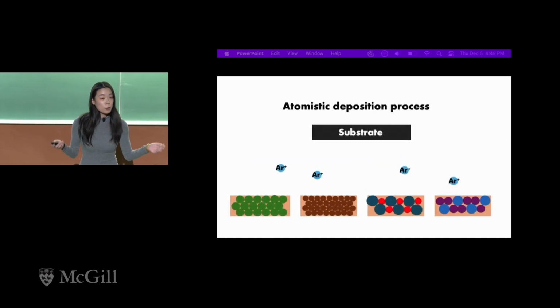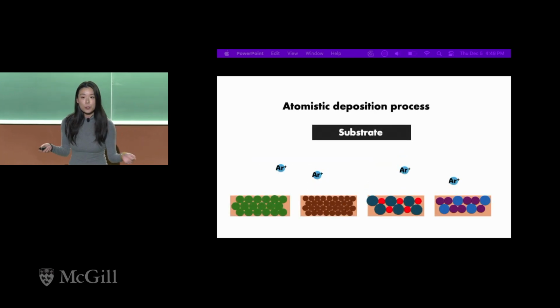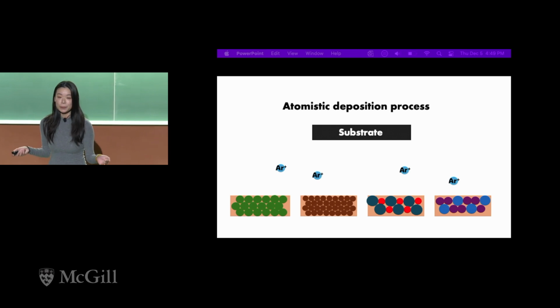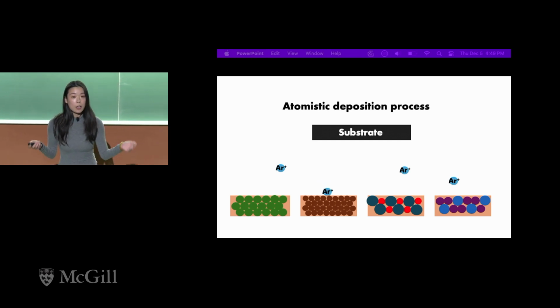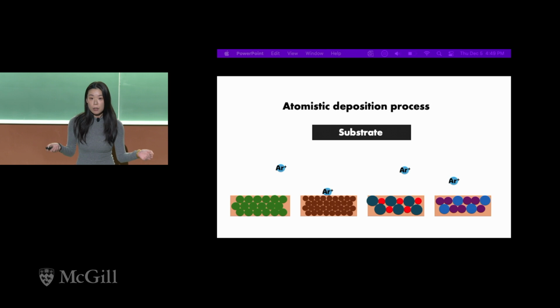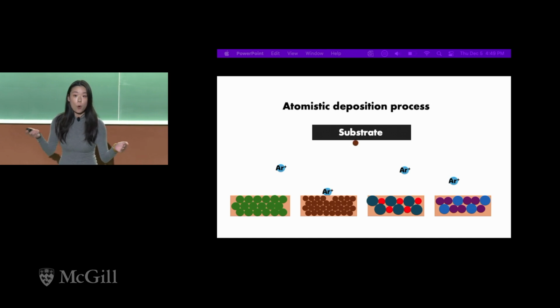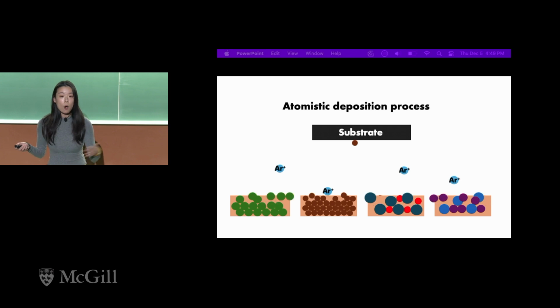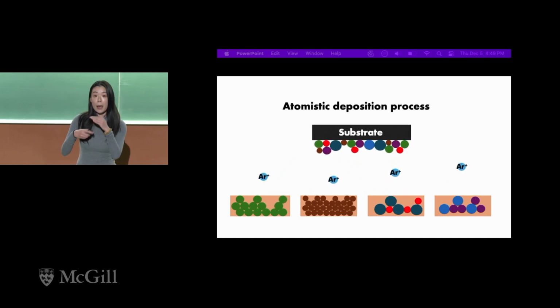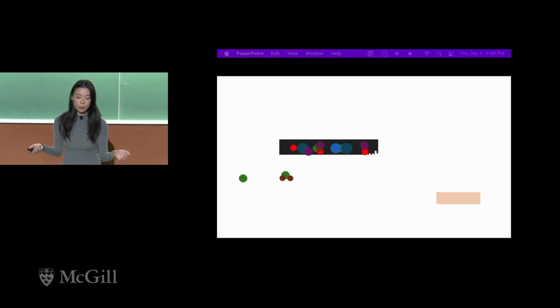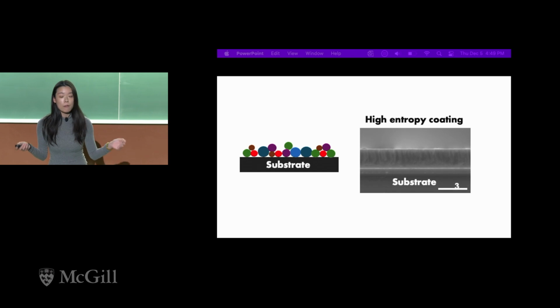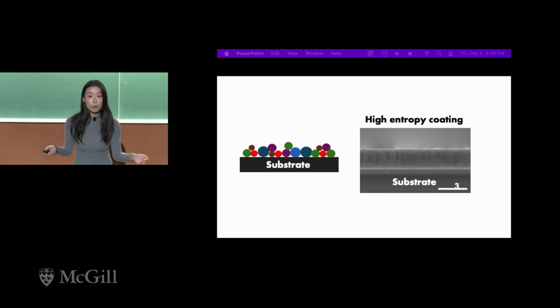So we then use an atomistic deposition process to create these coatings. In this process, the argon ions will bombard the target surface, causing atoms to be ejected from the target surface towards the substrate surface. And over time, we will build a layer-by-layer coating. Here is one example of our high-entropy coatings from this process. We then evaluate the wear resistance of these coatings using wear tests.